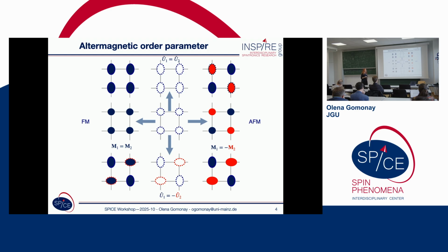If we are talking about the altermagnetic ordering or altermagnetic phase, then we go through this line, from a virtual imaginary phase to something which has an altermagnetic crystal structure, and then look at the magnetically ordered phase. Or we can even go this way: we can imagine that first our lattice becomes antiferromagnetically ordered, and then it transforms to the altermagnet. Whether this transition is real or imaginary, I don't know, but by introducing this separate altermagnetic order parameter, I have a tool which allows me to see what altermagnetism brings into my system compared to the antiferromagnets.